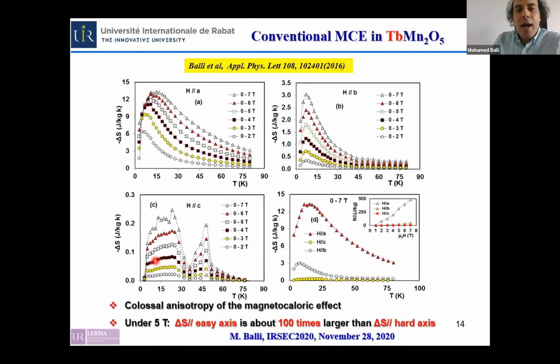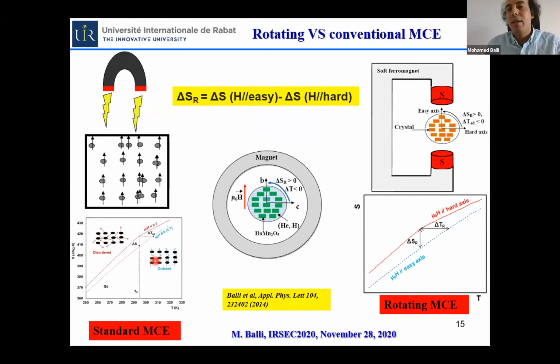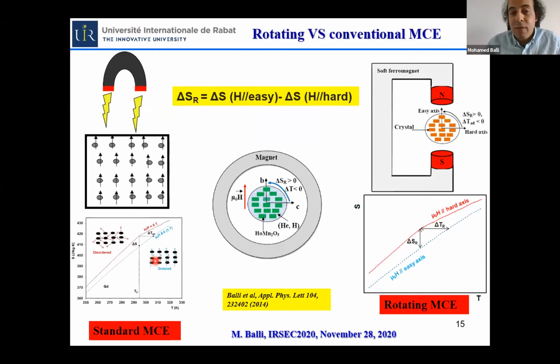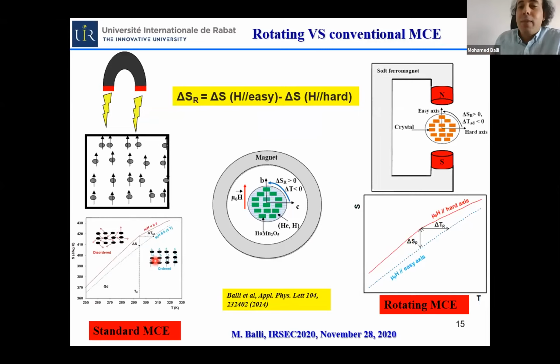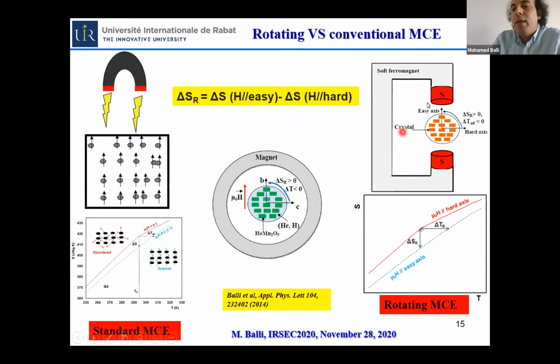As I explained before, in addition to this conventional magnetocaloric effect, this family of compounds presents a giant anisotropy of magnetization and magnetocaloric effect. So in addition to the conventional magnetocaloric effect obtained by magnetizing and demagnetizing these materials, additional caloric effect can be obtained, as shown here, by rotating their single crystal between the easy and hard magnetization axis.